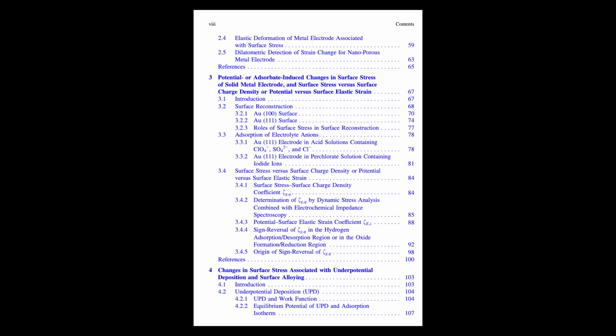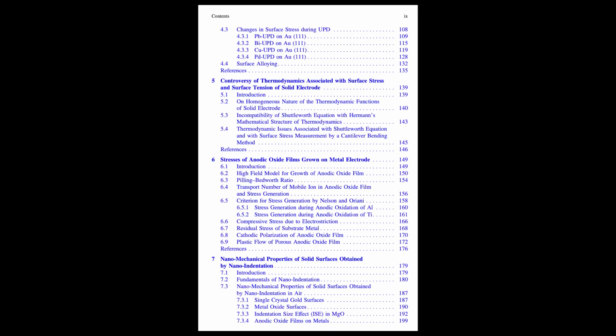Really? Yeah, for example, on gold (111) in perchloric acid, that reconstructed state lifts, it disappears, around -0.2 volts relative to a saturated calomel electrode, SCE. And this transition comes with significant changes in surface stress. Wow. So just by tweaking the electrical environment, we can basically tell the surface atoms, okay, go back to normal, or adopt this new pattern. And those tiny atomic shifts have a real mechanical effect, changing the overall stress.